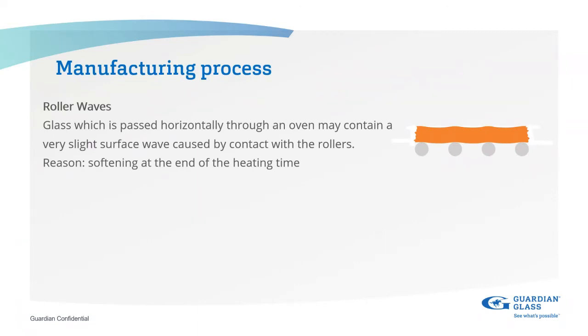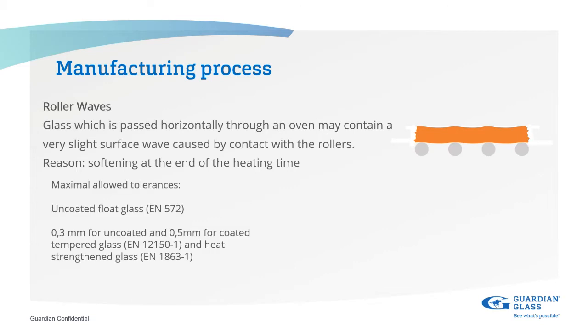Roller waves, as I explained earlier, is where the roller wave is imparted into the tempered glass during the heating process. So basically what happens here is the glass, as it oscillates inside the furnace, picks up the pitch of the rollers. So you actually get a very slight surface wave on the glass, and it can be seen sometimes when it's glazed at sight. This is basically caused by the softening point at the end of the heating time. The maximum allowed tolerances are 0.3 mm for uncoated and 0.5 mm for coated. This is according to EN 12150 and EN 1863 for heat strengthened.